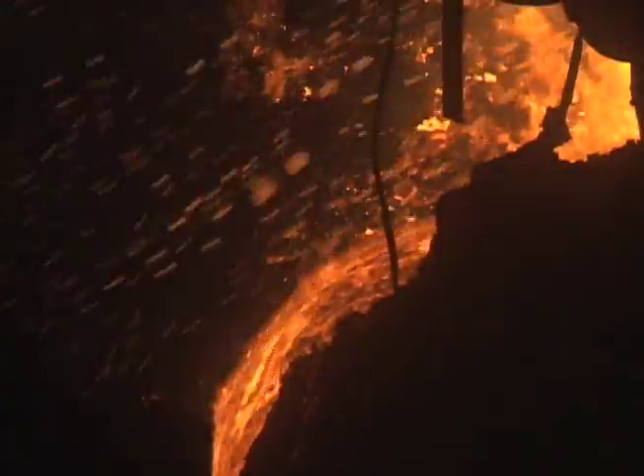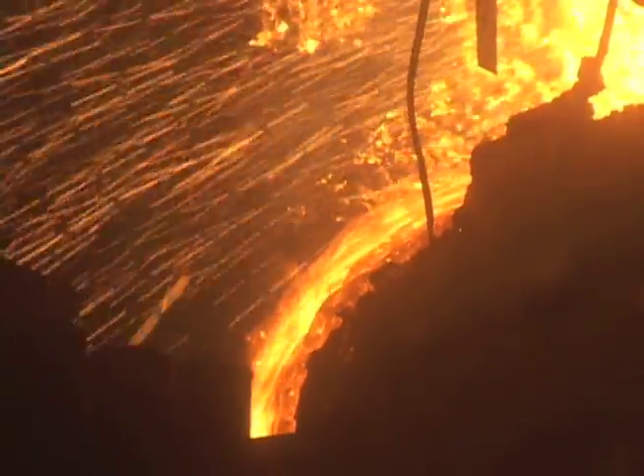The foamy slag is a practice that creates a carbon monoxide and carbon dioxide enriched slag that engulfs the electric arc and directs the energy of the arc down into the liquid metal bath to promote more efficient heating. The foamy slag has the additional benefit of protecting the furnace walls and roof from the detrimental and inefficient radiant heating that occurs without slag foaming.